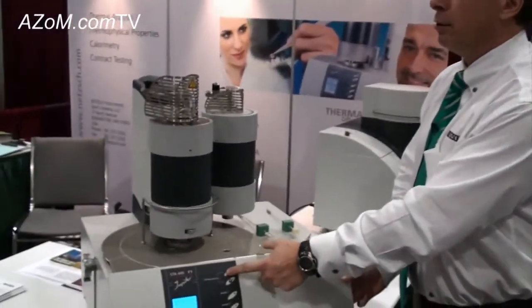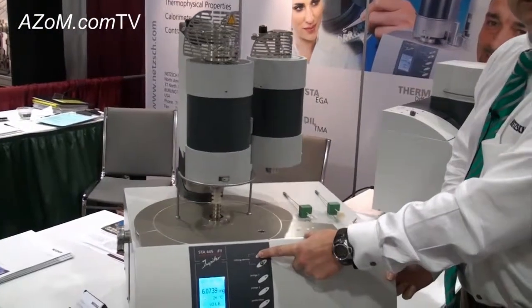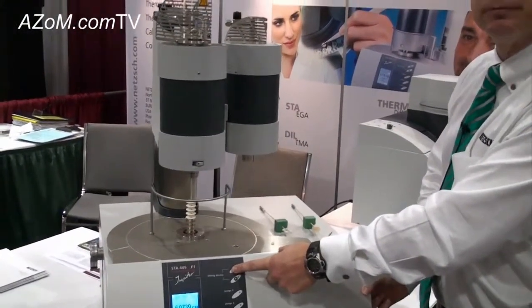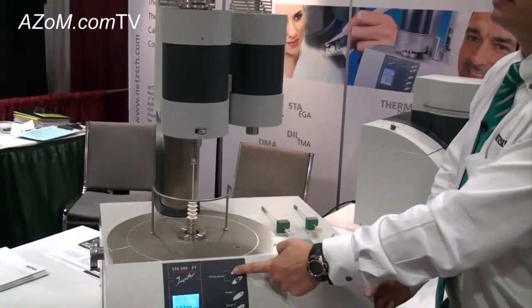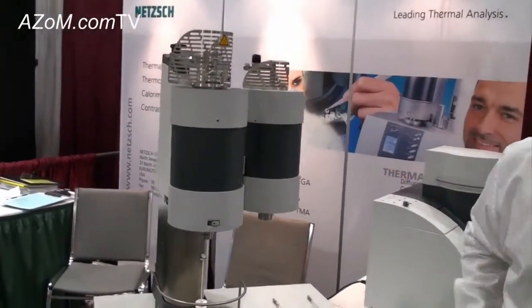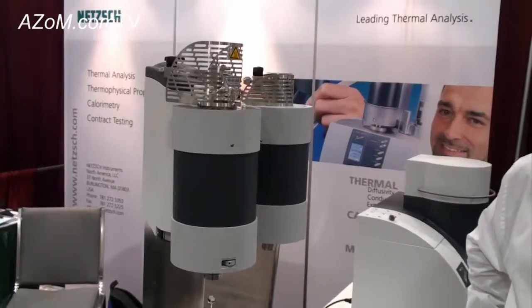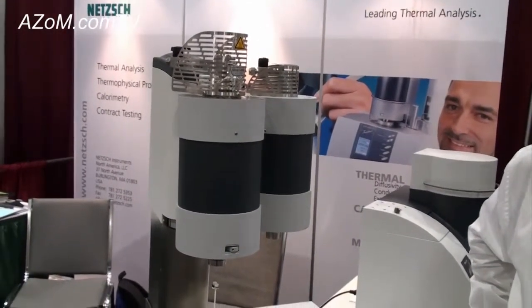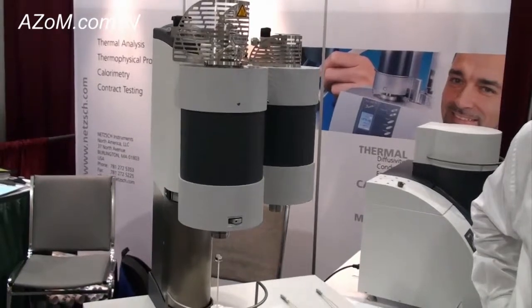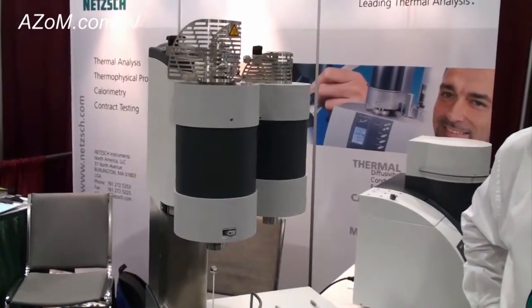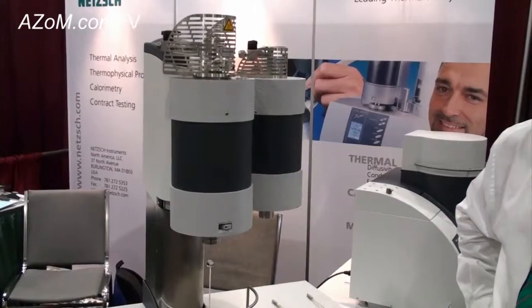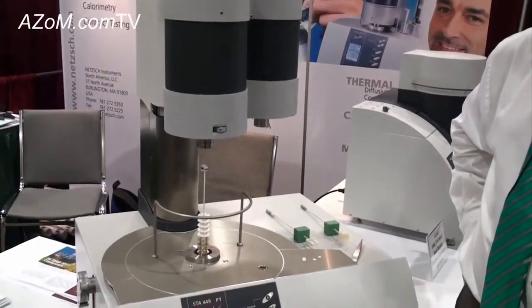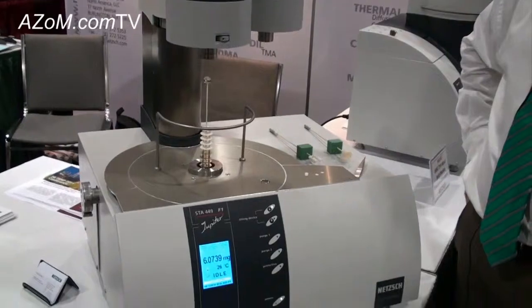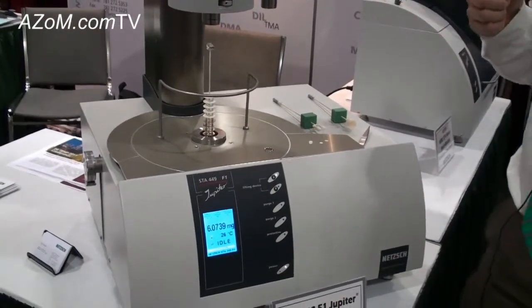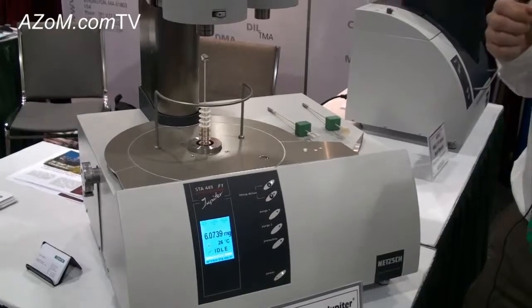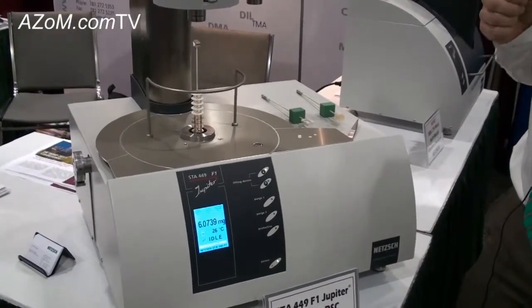We can operate over a wide range of temperatures depending on the furnace that we use. The standard furnace is this silicon carbide furnace, which runs from room temperature up to 1550 degrees Celsius. We have other furnaces that could go up to 2000 degrees or even up to 2400 degrees C. And on the low temperature range, we could go down to minus 150 degrees C up to 1000 degrees C. So we could actually measure DSC and TGA instrument measurements in one measurement from minus 150 up to 1000.